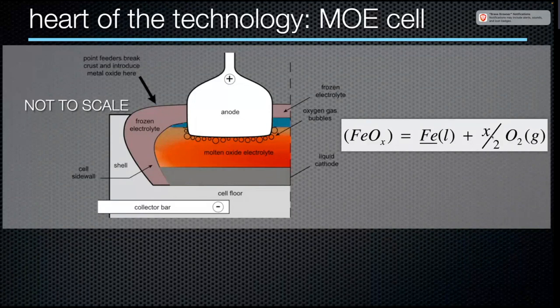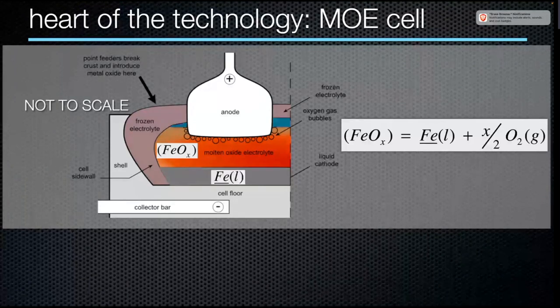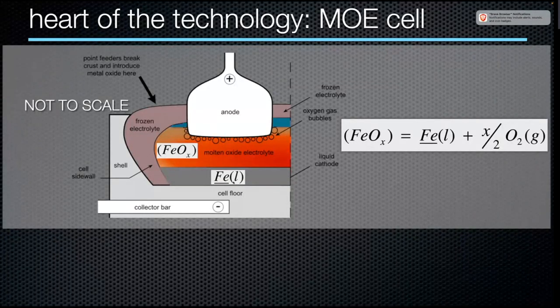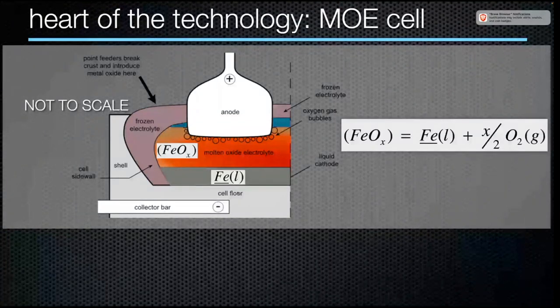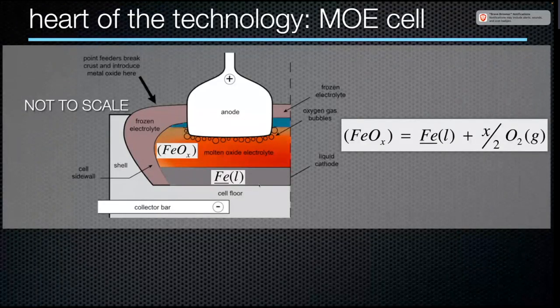And so let's take a look. So this is the solvent for the iron oxide feedstock. And by the action of electric current, we make liquid iron, which pools at the bottom of the cell. And the iron pools on top of the cell floor. This is probably a carbon floor. And the liquid iron itself is an electronic conductor. So at this interface between the molten oxide electrolyte and the gray zone here, which is the liquid iron, we continue to accumulate more and more liquid iron.